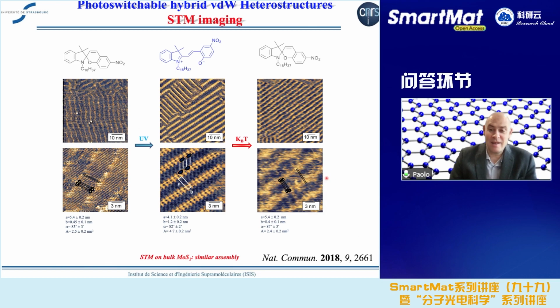Otherwise, it's the identical surface of graphite, the one of graphene. Likewise, MoS2. I think the major challenge is the one of being able to transfer a large flake of MoS2 onto a flat surface that can be insulating, like silicon dioxide. Once this is done, then the generation of a film exploits some knowledge that has been developed in the last 30 years. So physisorption and long alkyl chain or big aromatic system helps to get an extended self-assembled physisorbed monolayer. So that is doable. I don't see a major problem with this.